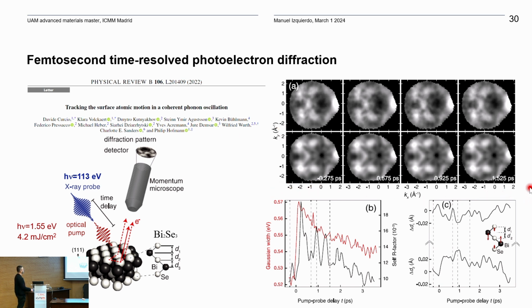as a function of time, and then you can also extract some time traces, and you see either the Gaussian width or the R-factor as a function of time, and then retrace back to the distances of the layers in the material. Basically, they monitor the changes of the distances D1 and D2, which are the two surface-most layers of the system, and what they see is some kind of anti-correlated movement, and this is due to the fact that this is mediated by some phonons.